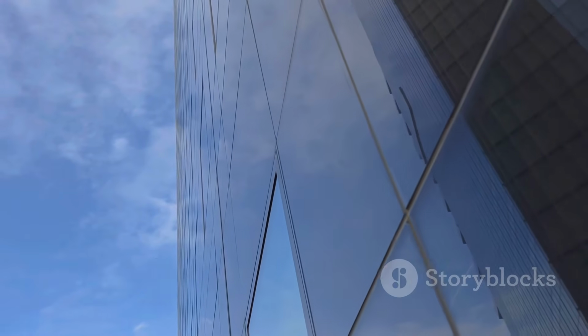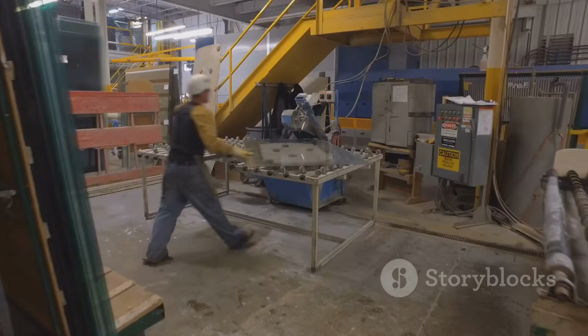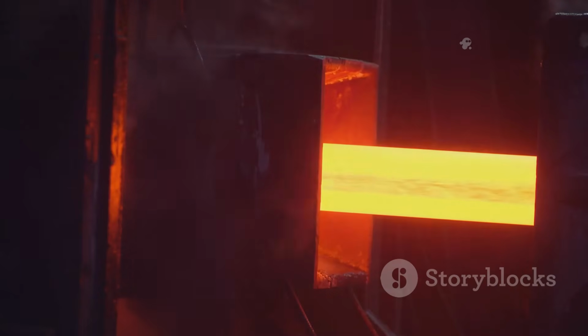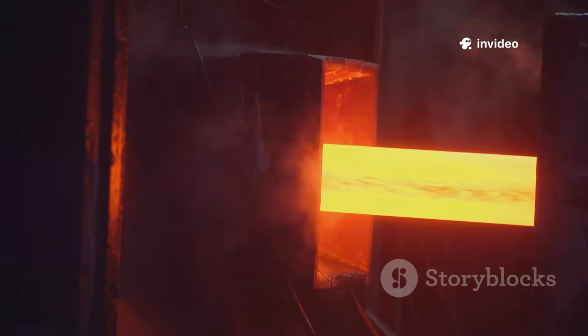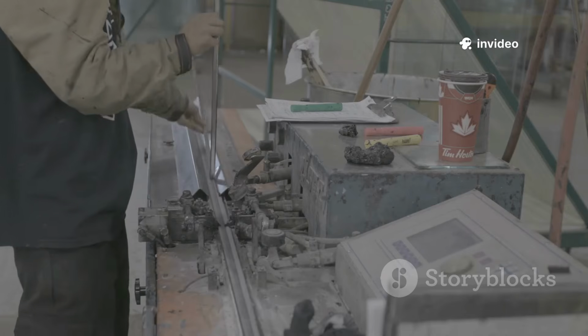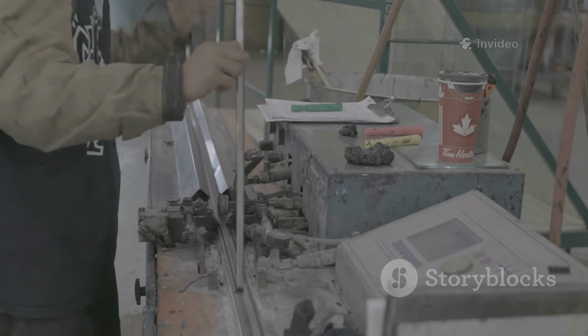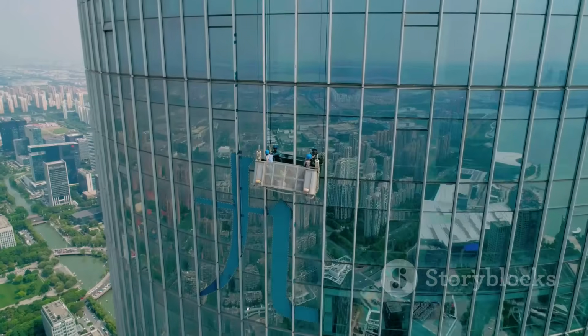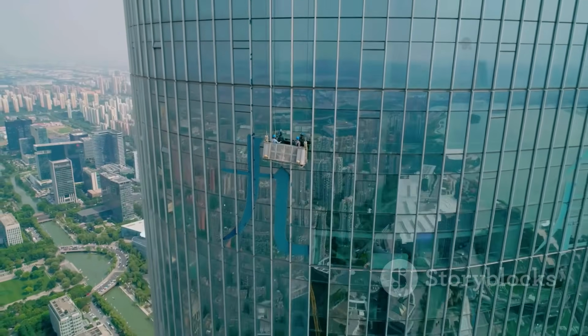For skyscrapers, glass must be even tougher and safer. Most architectural glass is tempered. Annealed glass is cut, then reheated and rapidly cooled, quenching. This creates compressive forces on the surface, making it 4 to 5 times stronger. If it breaks, it shatters into small, harmless pieces. Tempered glass is used in cars and skyscrapers alike.